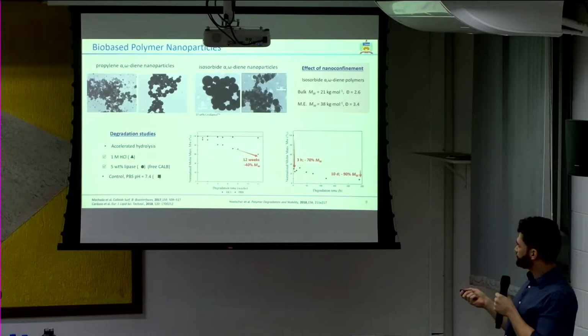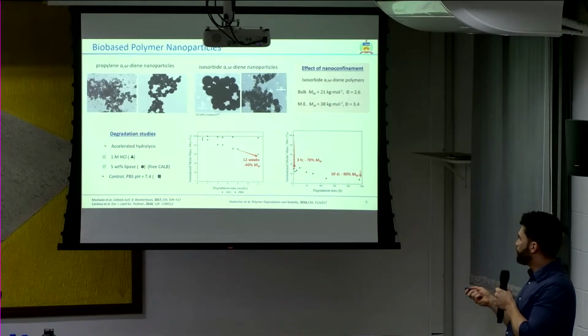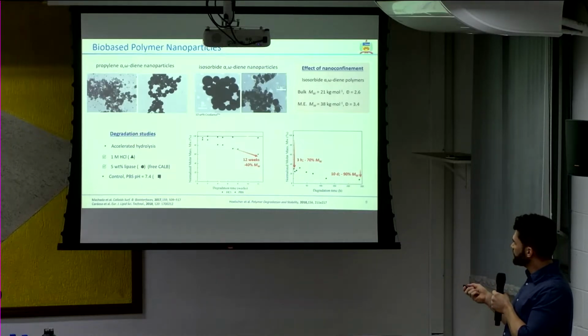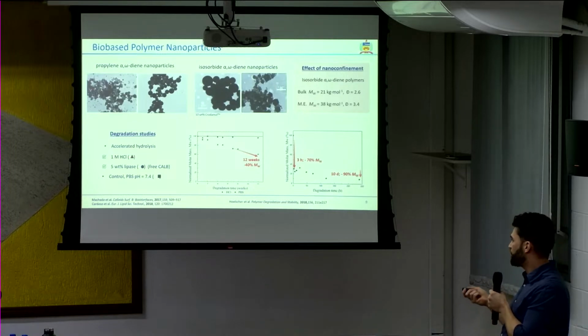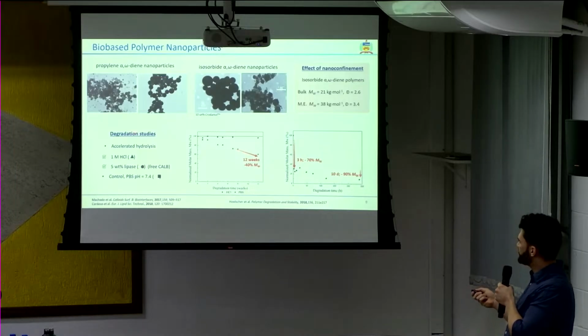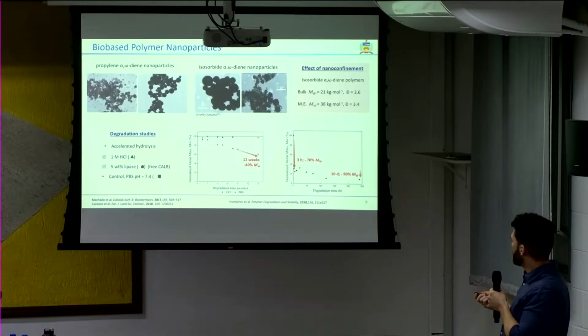Later on, we did some degradation studies with accelerated hydrolysis using acidic medium and also lipase, an enzyme. After 12 weeks in the acidic medium, the polymers degraded, they decreased 40% of their molecular weight, and in enzyme it was much, much faster. In 3 hours, the molecular weight decreased 70%, in 10 days, 90%, which is quite interesting. And the control was just PBS. That didn't change much.